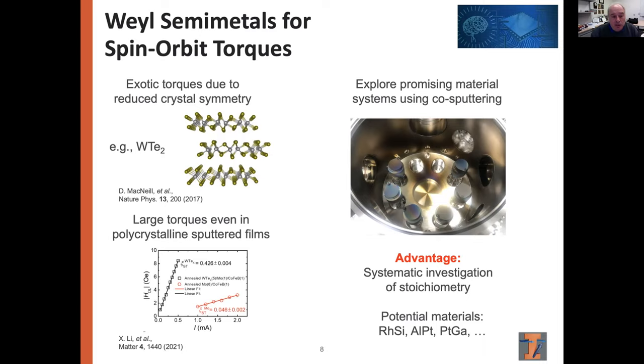Furthermore, it's been shown that you don't need to have single crystalline materials to do this. Polycrystalline materials perform rather well. And this has been shown in particular for tungsten ditelluride, where highly defective polycrystalline sputtered films were used for this purpose, and they perform exceedingly well.